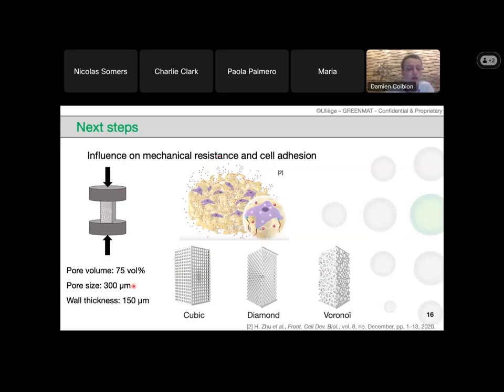So I decided to have similar properties to cancellous bone. As presented, it is the part which is porous in the bones. So we have quite a lot of voids because we have a pore volume of 75%. The pore sizes are close to 300 micrometers, and the wall thickness is about 150 micrometers. So I hope that I can present you these results soon, maybe in the next webinar or another meeting.